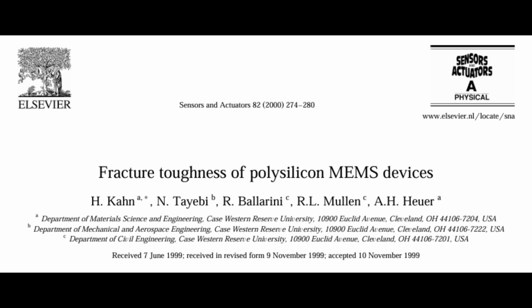And there's more. The process used to etch these notches, it can leave the sidewalls with different levels of smoothness depending on the technique. Okay. And that smoothness or roughness can actually influence how the crack behaves. So your results might end up telling you more about your etching method than about the polysilicon's inherent strength. So an artifact of the measurement method itself. Pretty much. The paper does mention some earlier work, people using external load cells, piezoelectric ones, or even wedge loading techniques on these notched samples. They got some numbers, some critical stress intensity factors, but still that underlying issue of the not quite sharp notch was always there, casting a bit of doubt.